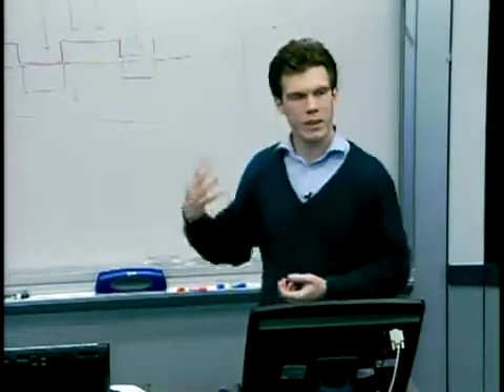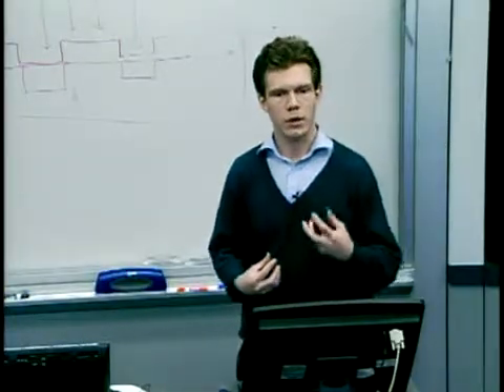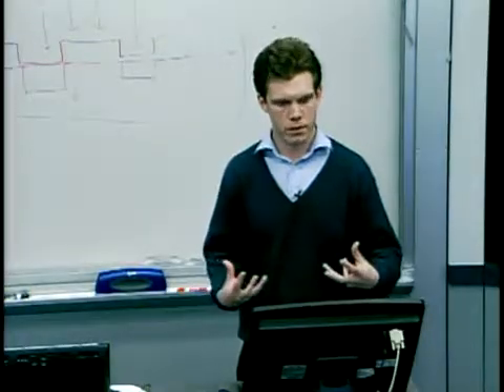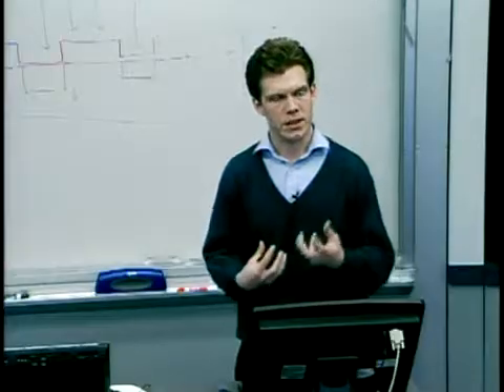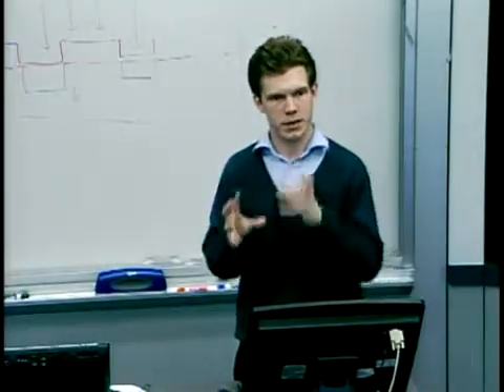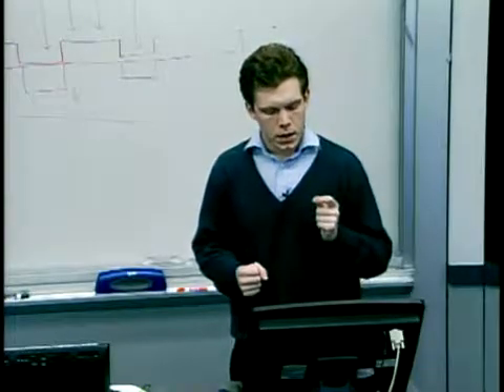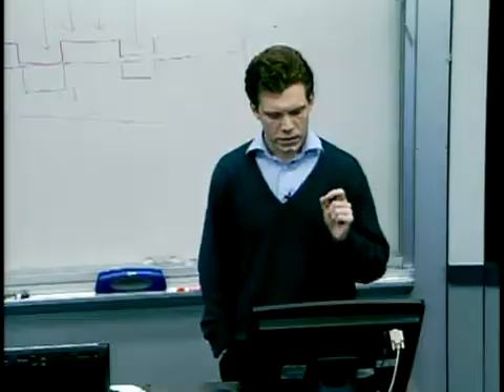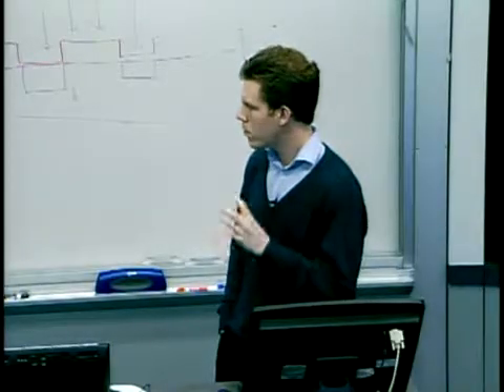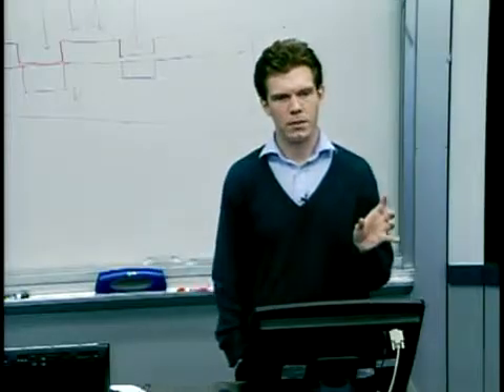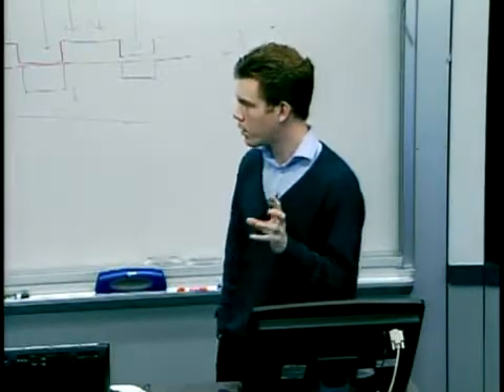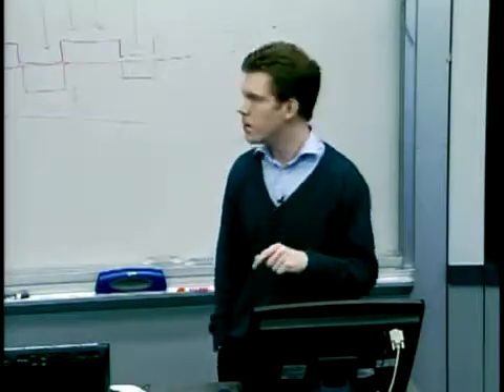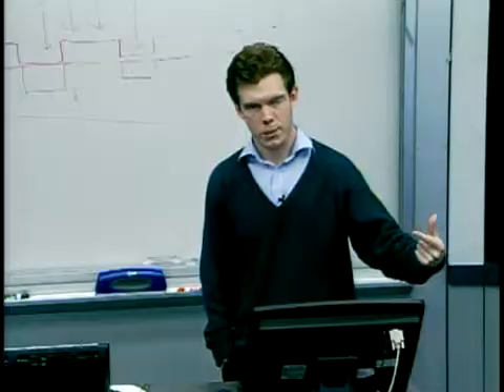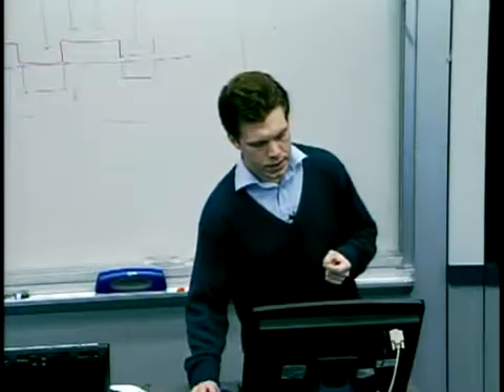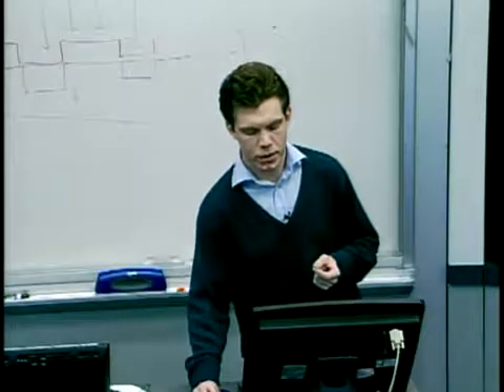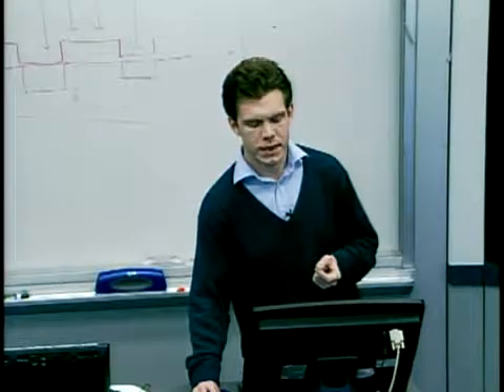But there's a one-dimensional implementation of that model that we can run. We can look at what happens when you give it various load profiles over time, and look at the stresses and the strains in each of those components of the model over time. So what I've done here is I've just done two, well, they're essentially thought experiments. The left-hand column of graphs shows what happens if the material is heated above its glass transition temperature, and then given 1.5 megapascal compressive load, which is held for 10 seconds.